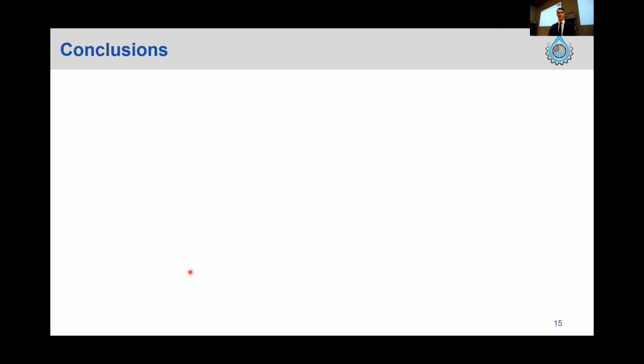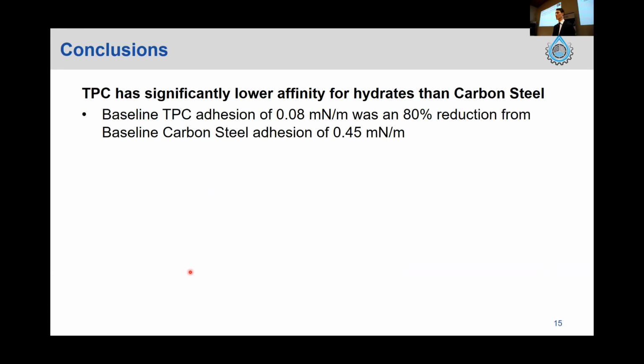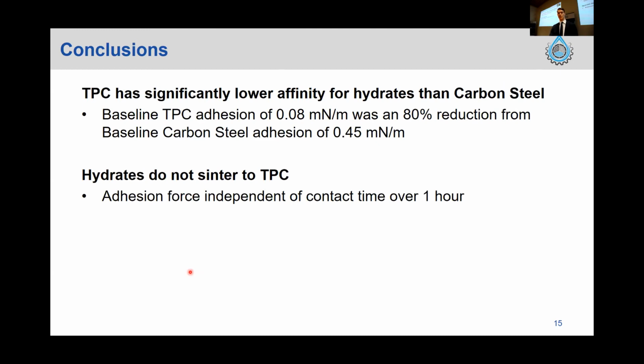So just to recap on those conclusions based on everything we've seen in the presentation, there was a significantly lower affinity of the TPC for hydrates than carbon steel, which was really promising, which was shown as an 80% reduction. The hydrates were shown not to sinter to the TPC with that longer contact time. And I forgot to mention, the takeout from that is that it's really encouraging for transient operations, when we can have shutdowns in flow and that flow potentially sitting in the pipeline for a longer period of time. That gives you a bit of confidence that they won't cause that problem to a higher degree than what might be seen in a different pipeline material.